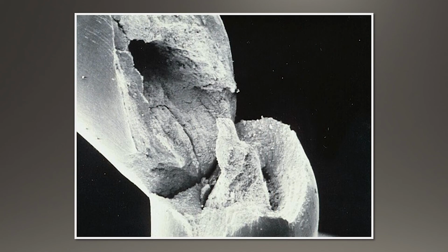Now, here's what I showed earlier. This end of the break over here, the cup end, does look very, very much like this over here, okay? But they're caused by different things, and it's so easy to get them mixed up. Generally speaking, if you are looking at the break, see if there's a 45-degree shear over here, which is an indication of a cup end. Because of the difference, I always recommend, even if it's banged up, if you're collecting wire breaks, to collect both ends, both the wire break that's in a machine and the end of the wire break that went through and maybe it was all banged up. Because this end, even if it's deformed, would look different than this end to show it's a cuppy wire break.